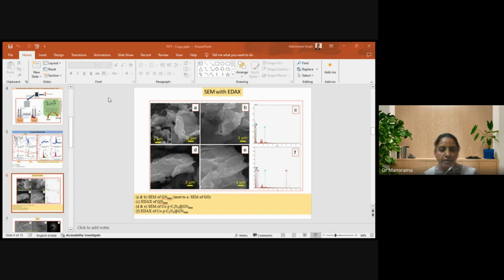This is the graphene oxide SEM, which is showing the transparent morphology, but when it is combined with the cysteine molecule, then the black spots are there, which generally is showing that yes, cysteine molecules are there. Then further, it has been combined with the cobalt doped graphite carbon nitride.